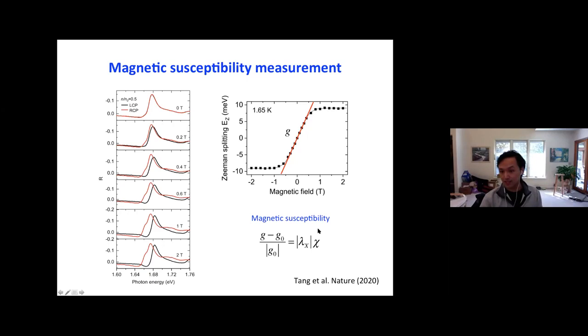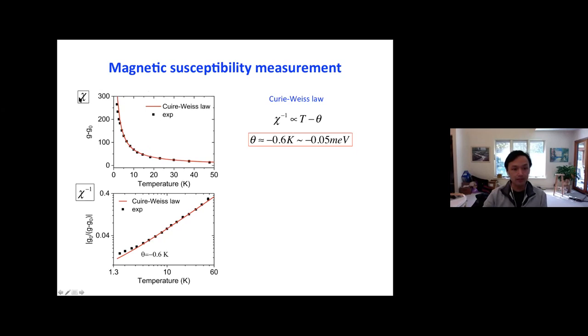But in terms of looking at the temperature dependence, this is sufficient. And this is the result for the G factor, which is proportional to chi, as a function of temperature, at a filling factor equal to one. The black dots are the data and the red line is the Curie-Weiss fit. This is one over chi, basically one over the data at the top. You can see that the Curie-Weiss law fits very well over a wide temperature range, over almost two orders of magnitude for the magnetic susceptibility.